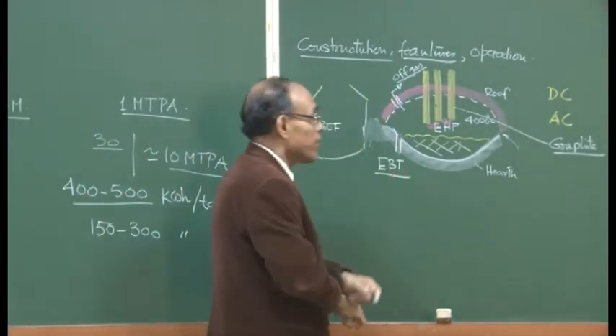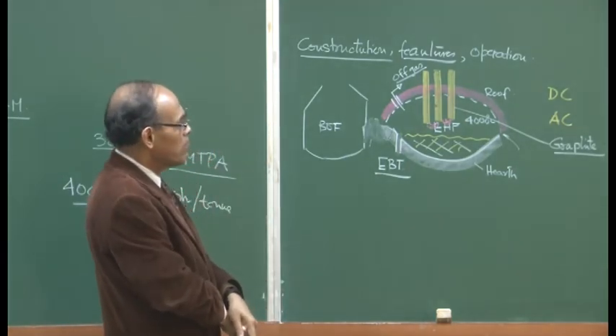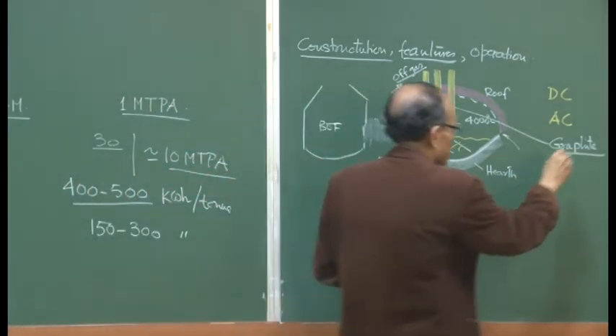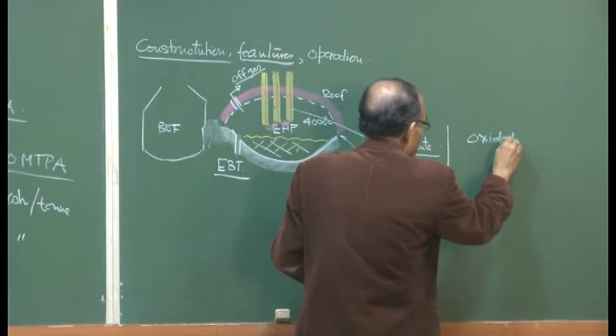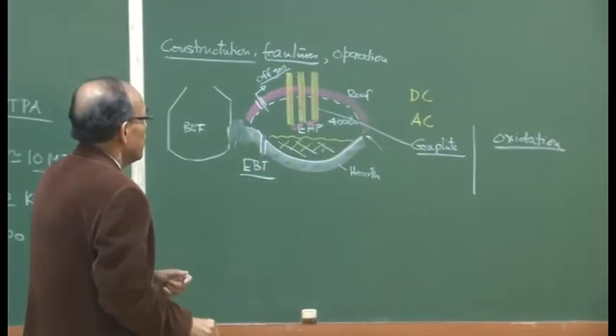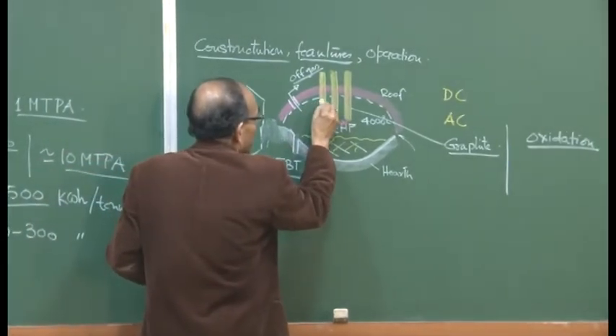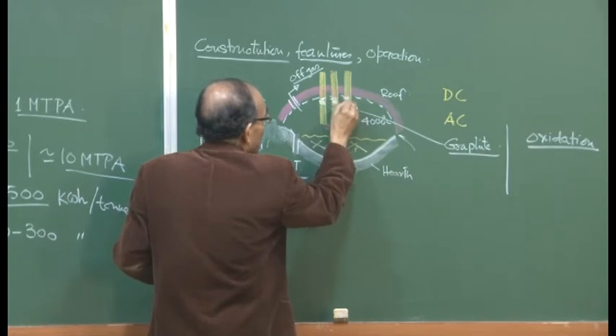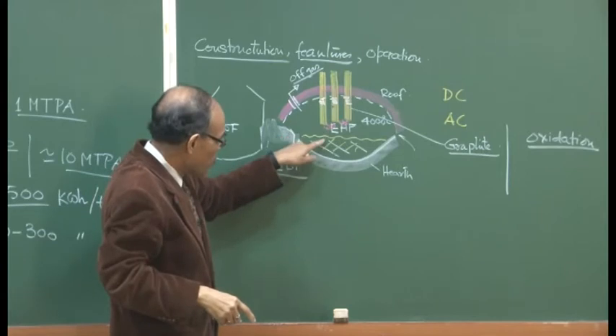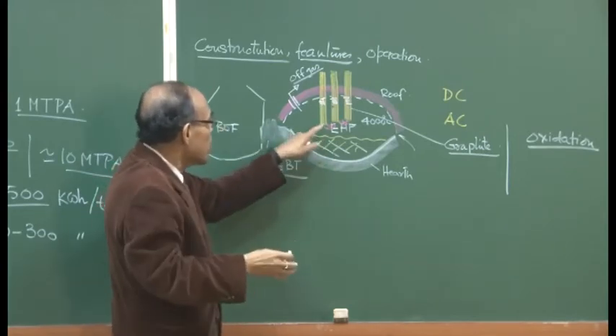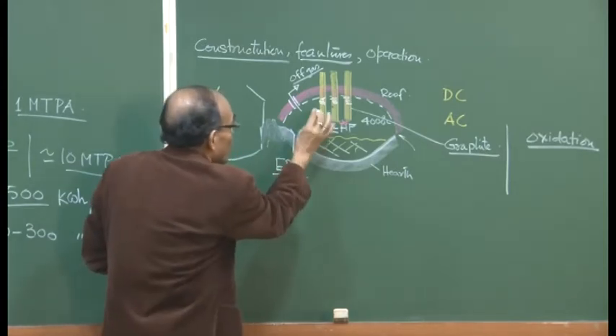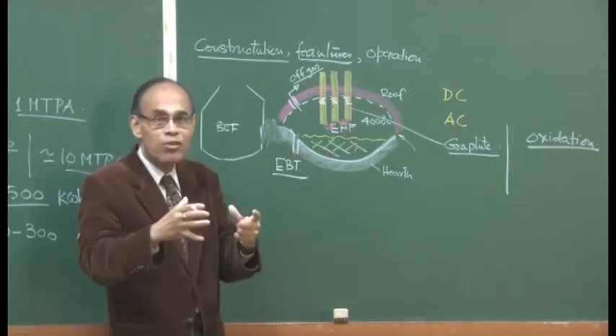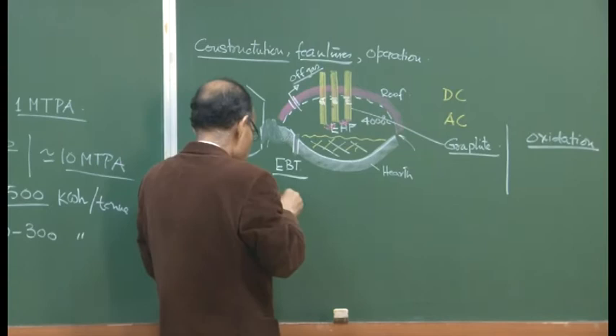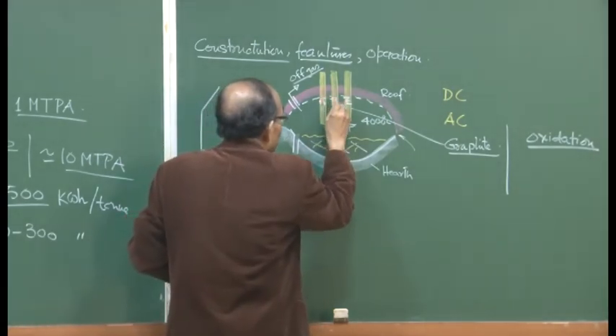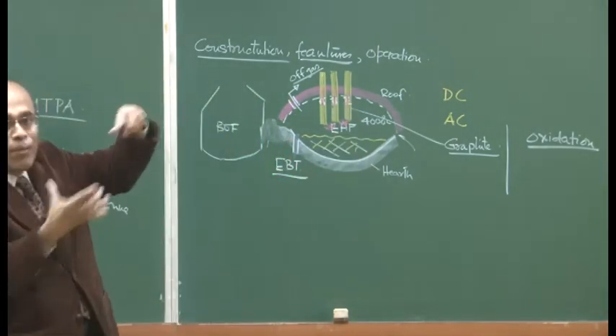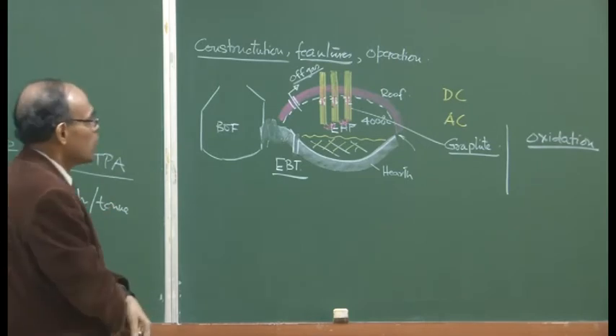These graphite electrodes are very expensive, as I have indicated, and the graphite basically undergoes quite a bit of oxidation. There is mechanical degradation, of course, and you have coupling arrangements here, screwing arrangements. So, the upper part is not replaced. If the lower part, which comes in contact with the molten metal or is exposed to a harsher environment, gets consumed, one can unscrew the lower part from the top part and then bring in a fresh lower part and screw it onto the upper part. So, there are coupling arrangements so that the upper and the lower part can be combined with each other. That is just for convenience of operations.